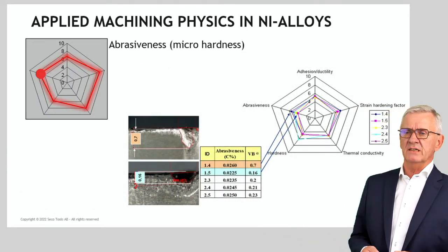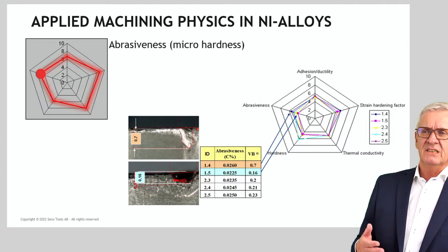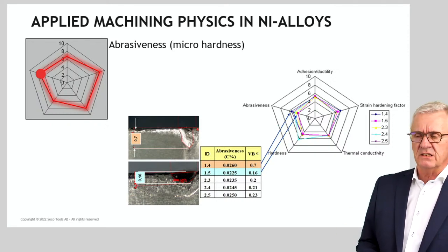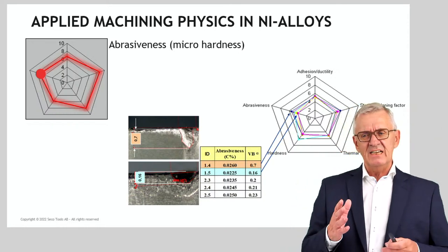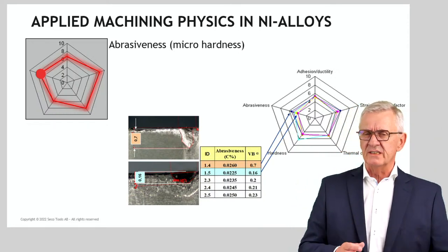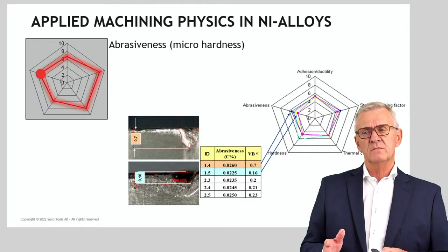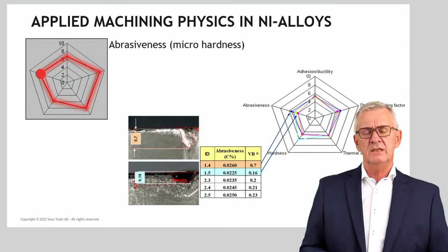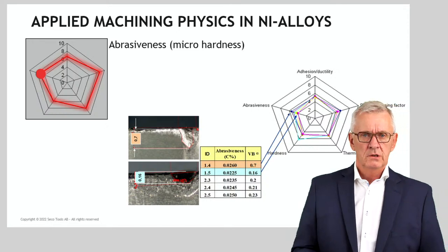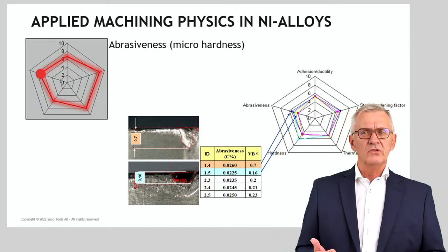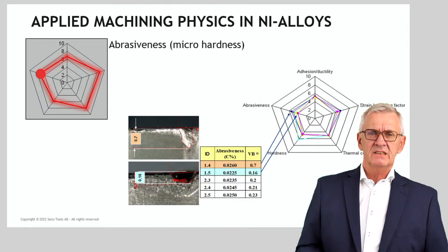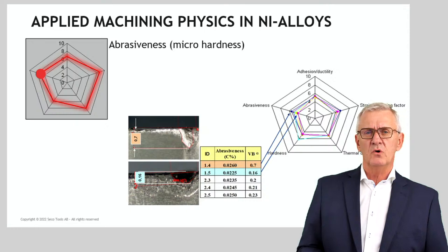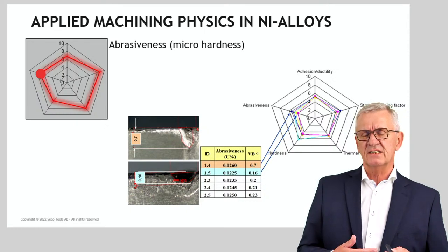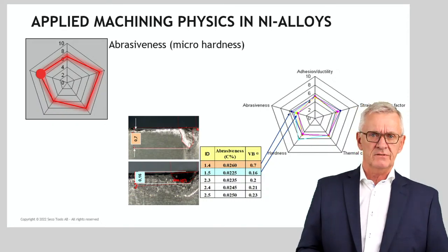From a more pragmatic respect, we learned through testing that abrasiveness kind of relates to the carbon content in materials. Now, what I'm showing you here is not really a scientific thing. It's just something we noticed in testing. But carbon content, especially in nickel-based alloys, titanium-based alloys, when you have more carbon, the material shows a tendency that carbides are formed in the structure, which leads to increased abrasiveness factors.